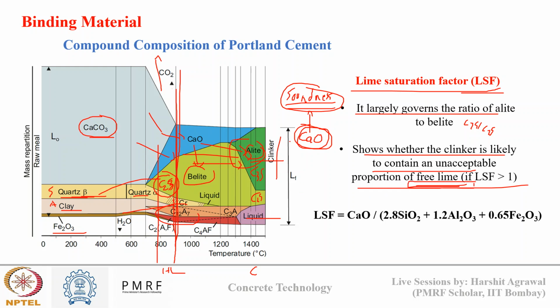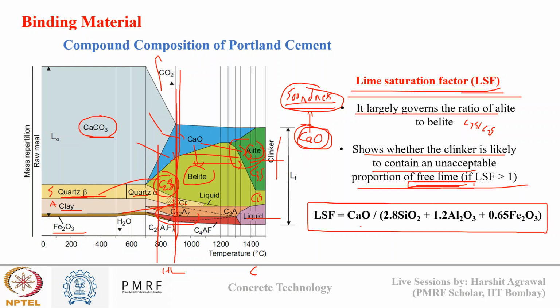So once the clinker is produced, we check this lime saturation factor. And how is it checked? Based on the oxide composition. If we know the oxide composition of the clinker we have produced, using this formula we can calculate the lime saturation factor. If this factor is more than 1, then we say that the clinker contained an unacceptable proportion of free lime, and thus that batch of cement needs to be rejected.